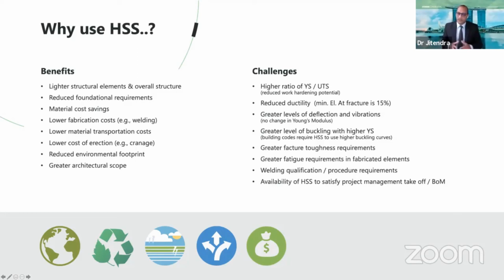The building codes restrict in some cases how high we can go in the strength of the steels, because it forces designers to use higher buckling curves, and there are greater fracture toughness and, in particular, fatigue requirements. Typically what we'll find is that as we go to very high strength steels, fatigue generally becomes the governing criterion, which limits how high we can go in strength. But as I said, going up to 460, generally we don't see that as an issue, and we're actually seeing 460 being applied to many structural projects in the market today.